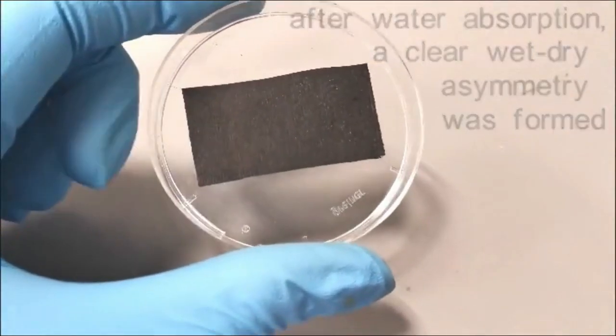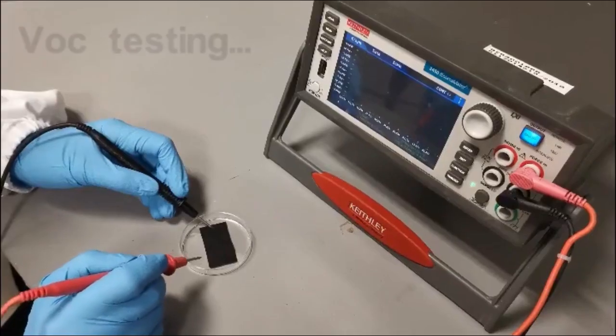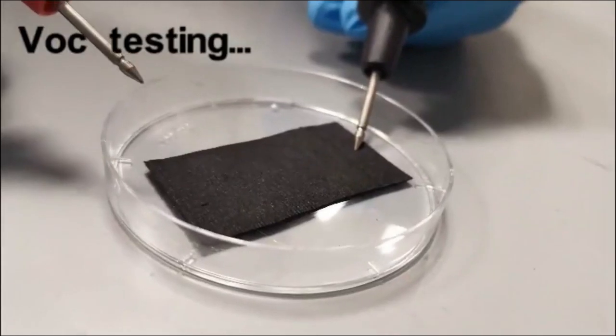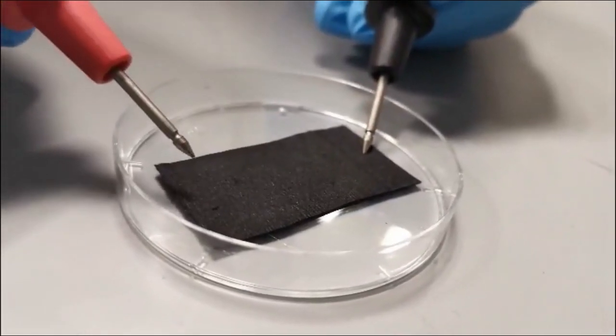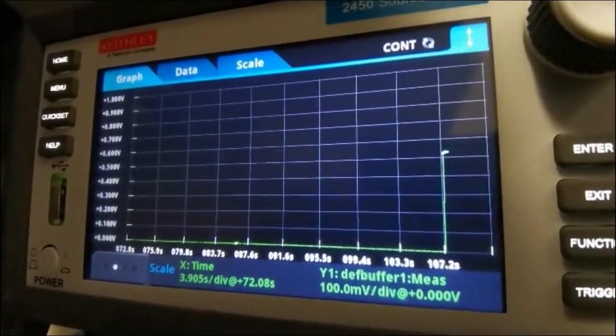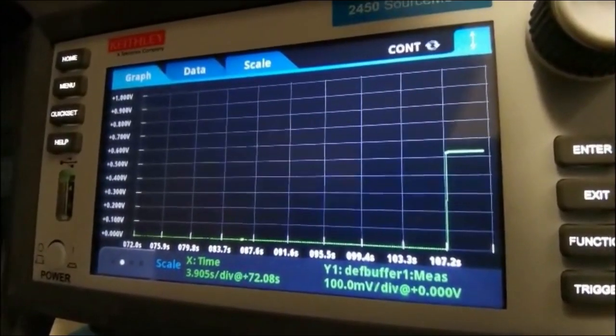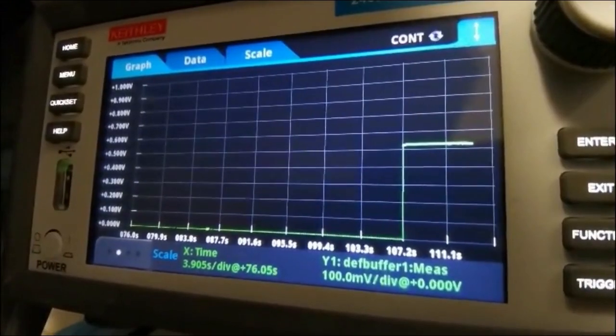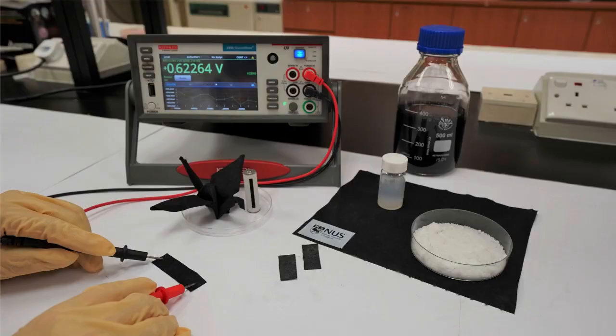Once the MEG device is assembled, electricity is generated when the ions of sea salt are separated as water is absorbed in the wet region. Free ions with a positive charge, cations, are absorbed by the carbon nanoparticles which are negatively charged. This causes changes to the surface of the fabric, generating an electric field across it. These changes to the surface also give the fabric the ability to store electricity for use later.